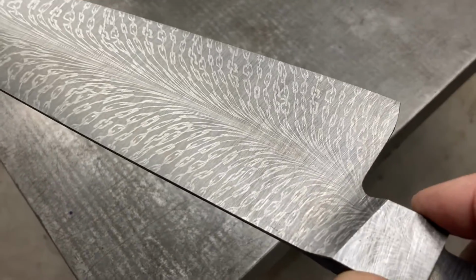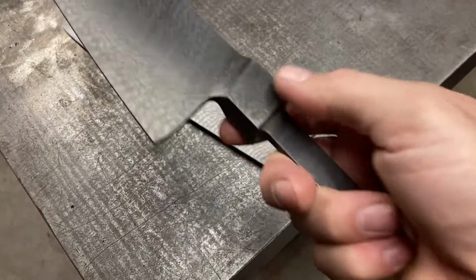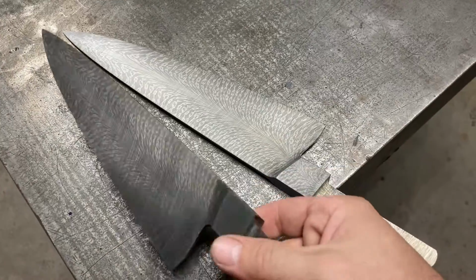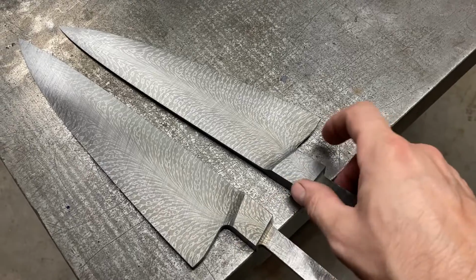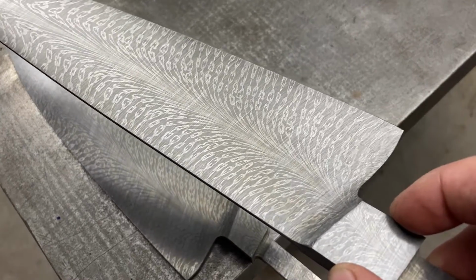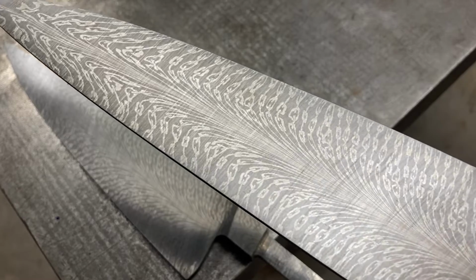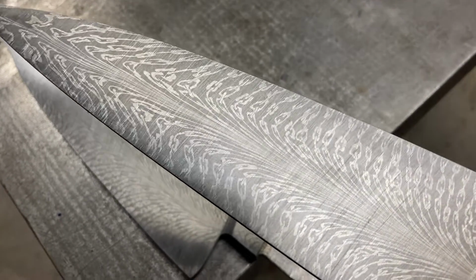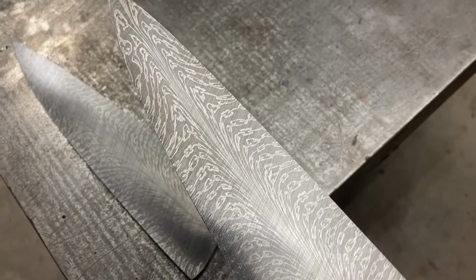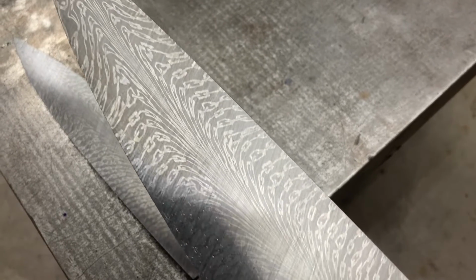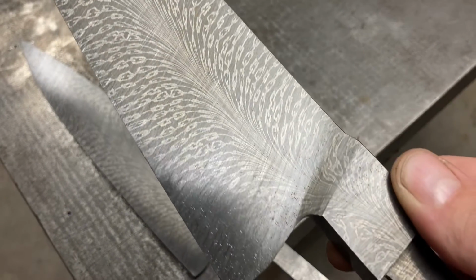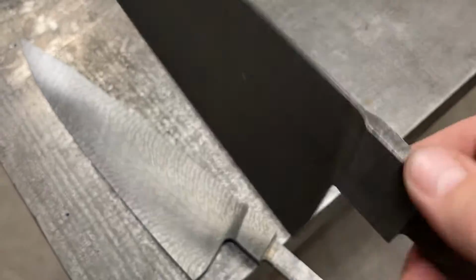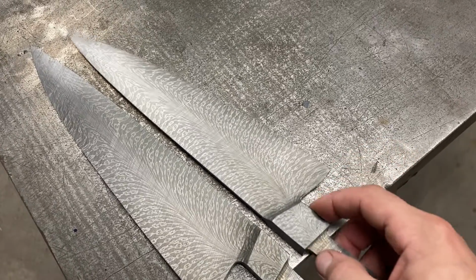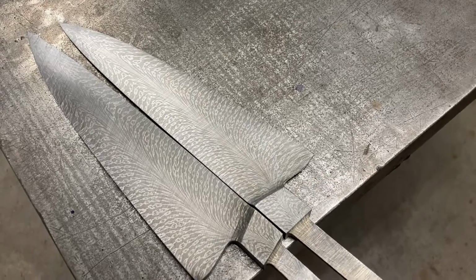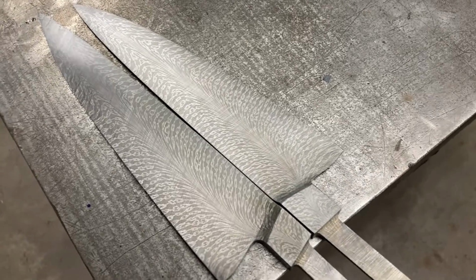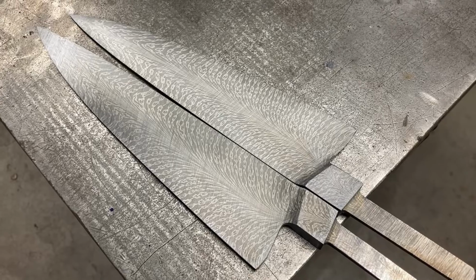Surface ground to 120 thou. And everything just blocked out, the tang and stuff, just to get it dimensional enough to heat treat well and not warp due to uneven mass. Same deal here. Forged in the tip. And good pattern in there, so just got this big old pair of feathers. We're gonna go stick them in the oven and get a nice hardness on them with that brand new Parks 50.